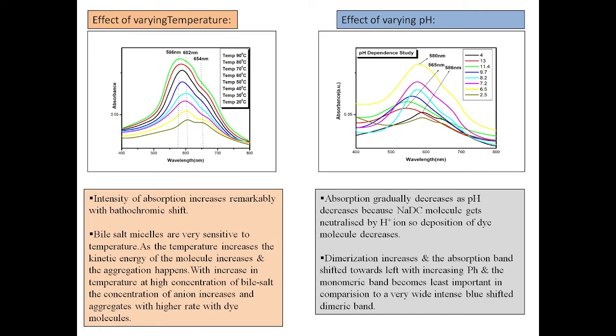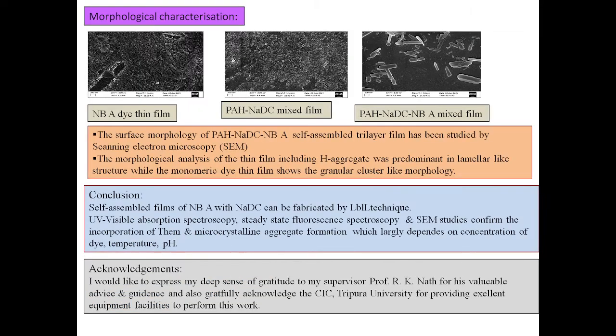Here we discuss the effect of varying pH on the film. We observe that the absorption gradually decreases as pH decreases because the NaDC molecule gets neutralized by hydrogen ions, so deposition of dye molecules decreases. Dimerization increases and the absorption band shifts towards the left with increasing pH. The monomeric band becomes less important in comparison to a very wide, intense blue-shifted dimeric band.